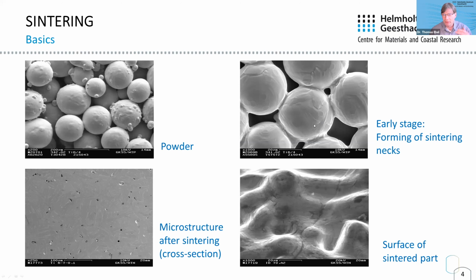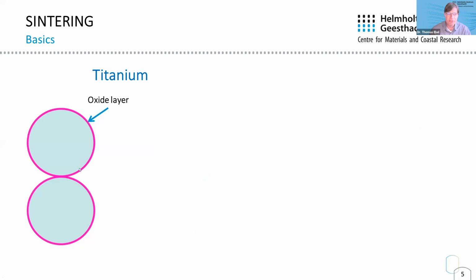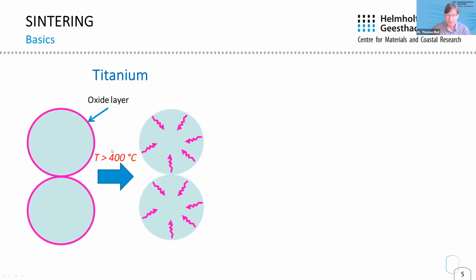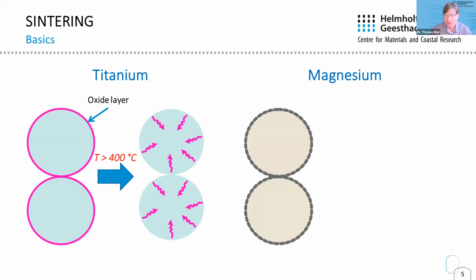especially this first process relies on the cleanliness of the surface. And on metals, you have usually an oxide layer, and this oxide layer can hinder sintering. To be honest, these images here are titanium. In the case of titanium, it is quite nice because the oxide layer, which is in principle a very stable one, dissolves at temperatures above 400 degrees. And then the oxygen is just diffusing into the powder particles, and the surface itself is pure metallic. So it's very nicely sinterable. Titanium works really nice. In the case of magnesium, it's a little bit different. You have, again, an oxide layer, but this oxide layer is stable until melting of the material. And this oxide layer really hinders the sintering.